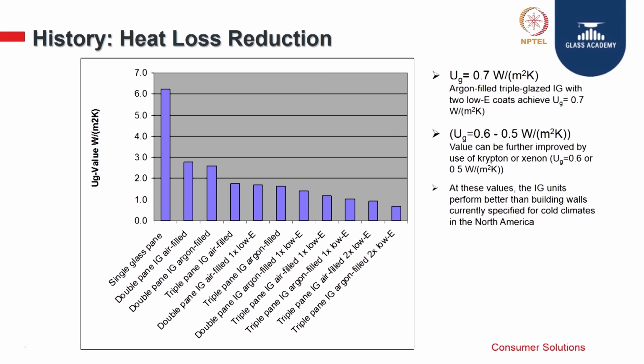By doing different combinations of triple, low E coating, gas filled, and then argon or krypton, you can do combinations of that. You can have a low E coating with argon or a low E coating with krypton, and then different types of low E coating, single, double, and different types of double and triple panes, the U value can be reduced. Today the U values are achieved to the best, which are essentially good for cold climates, and also sometimes for our own climates, but what is important is that U and the solar heat gain both go hand in hand.